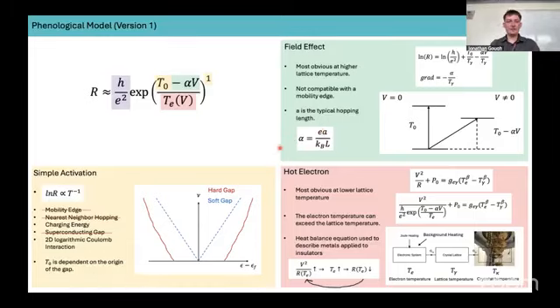We also include a voltage dependence through the electron temperature. Electron heating in metals and dirty metals is very common because the electrons can essentially drift in the electric field over large distances without interacting with a bath. However, in variable range hopping, you're constantly interacting with the bath through this inelastic scattering event that maintains hopping. However, we're making the assumption that this variable range hopping mechanism isn't working in the regime that we're in.